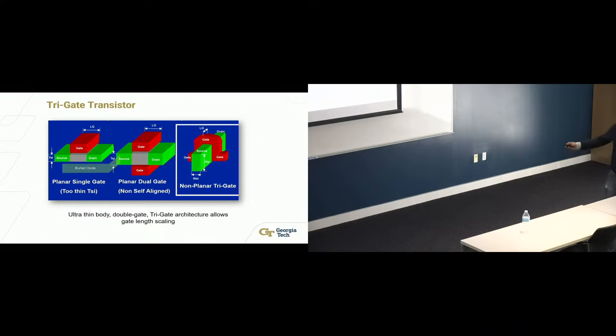So, one idea that was coming out from IBM was that if you cannot control the leakage path away from the gate, then why don't you put a buried oxide, aka SOI, silicon on insulator. So you make a silicon on insulator, you have a buried oxide, and you make this body of the silicon as thin as possible, okay? So that way you don't have to worry about those leakage currents.